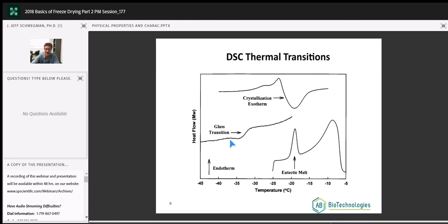Glass transition, all it is, is a shift in viscosity. So below the TG prime, we have a rigid solid. As it warms up, molecules start to flow, there's no breaking of bonds, no crystals tearing apart, lower energy event. Unless we look for this, we won't find it, we won't see it, okay? So we always have to go back to our baseline and look for this.